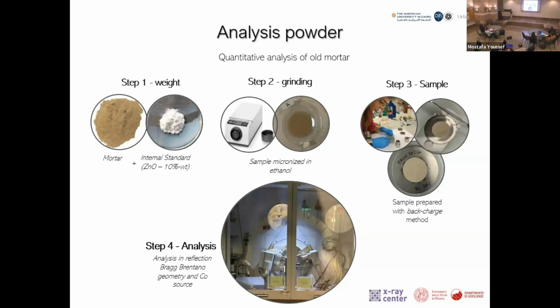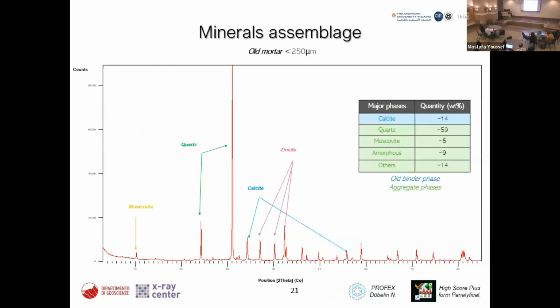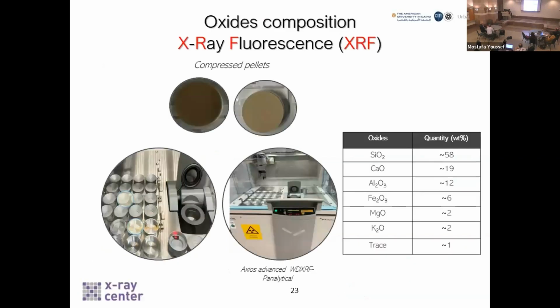I prepared the sample with the backload method, and I simply analyzed the sample with the diffractometer in reflection and Bragg-Brentano geometry. After that, here I reported the result of my analysis, and as you can see, I was able to find two principal phases. The blue one is related to calcite, and this represents the real binder of my mortar. And moreover, I was also able to detect quartz, muscovite, feldspar, and other minor phases that instead are related to the presence of the aggregate in my mortar.